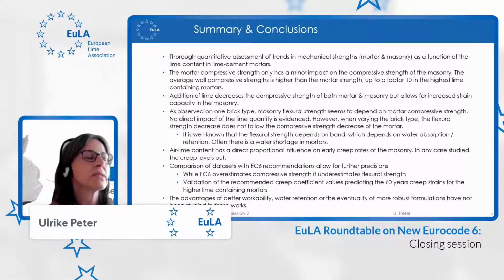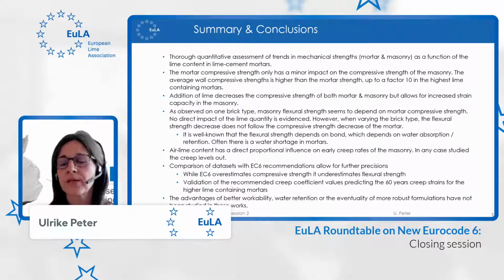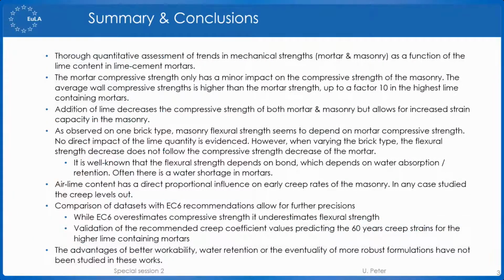What has been shown in these 2 presentations is that the mortar compressive strength only has a minor impact on the compressive strength of the masonry. I think that this was already known before. And it was shown that the average wall compressive strength is higher than the mortar strength in average. And in the case of the weakest mortars, it is up to a factor 10 higher than the compressive strength of the lime-containing mortar. It is also shown that addition of lime decreases the compressive strength in both the mortar and the masonry, but it also allows for an increased strain capacity of the masonry.